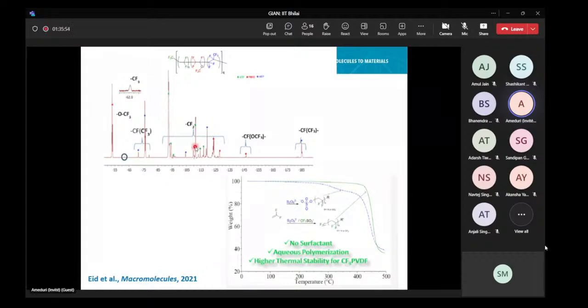Another one is linked to VDF adjacent to HFP. Another one is linked to VDF adjacent to PMVE. This is linked to the presence of a CF in perfluoromethyl vinyl ether, and the CF3 here is at -53. So you have a very nice resolution of your spectrum. The CF of HFP is at -180, and from the different integrals, it's possible to calculate the molecular weight. Of course, we have to be very careful because we might have some error, about 5 to 10%, but in this case we have a molecular weight of about 50,000.